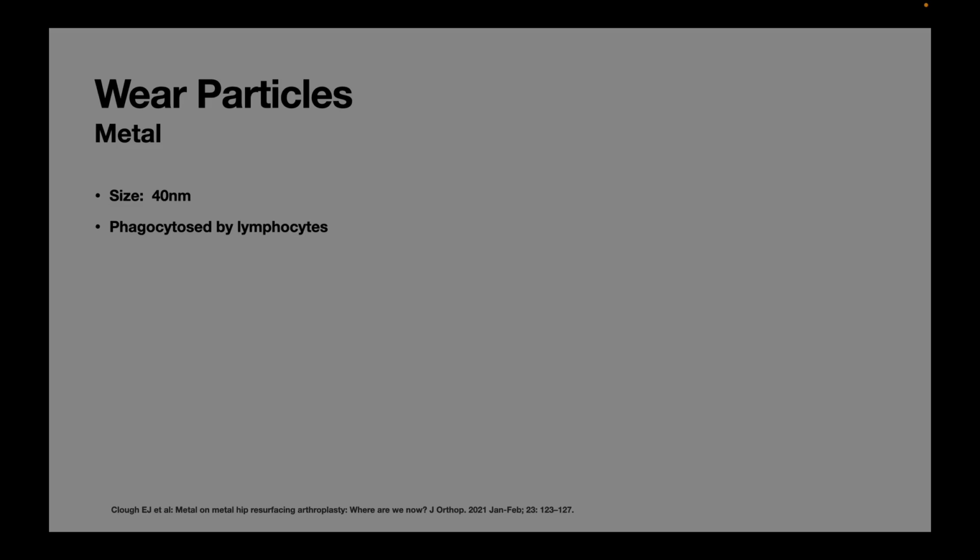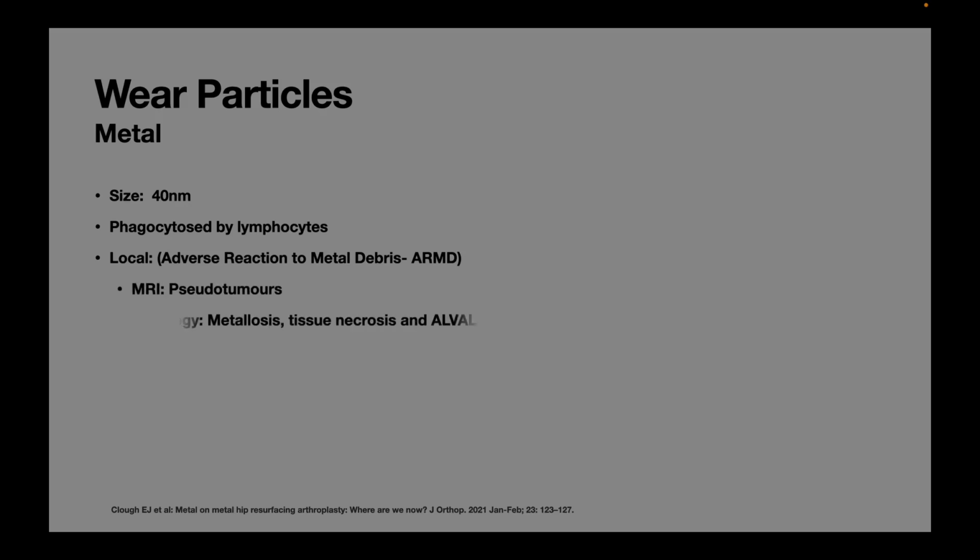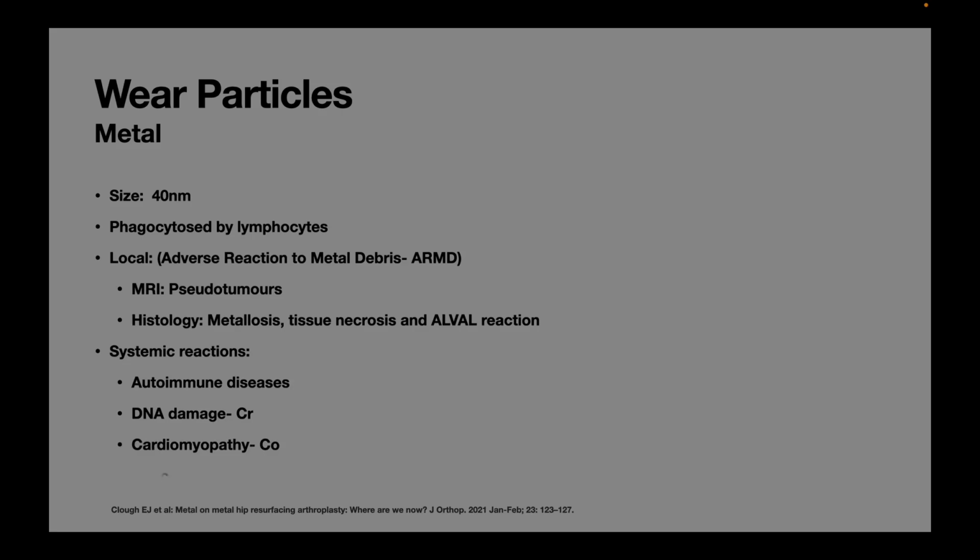The local soft tissue effects, also called adverse reaction to metal debris, can be appreciated on an MRI as pseudotumors and histologically in the form of metallosis, tissue necrosis, and ALVAL reaction. Some of the systemic effects of metal wear particles are autoimmunity, usually to nickel, DNA damage due to chromium, cardiomyopathy, and oncogenesis due to cobalt.